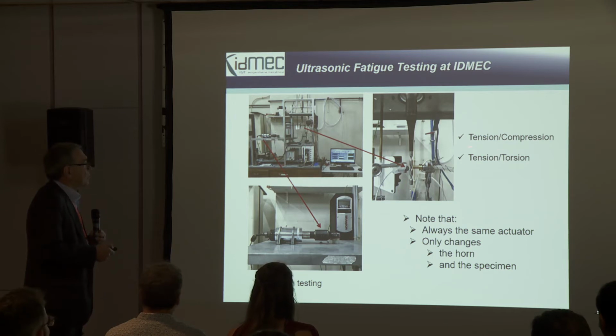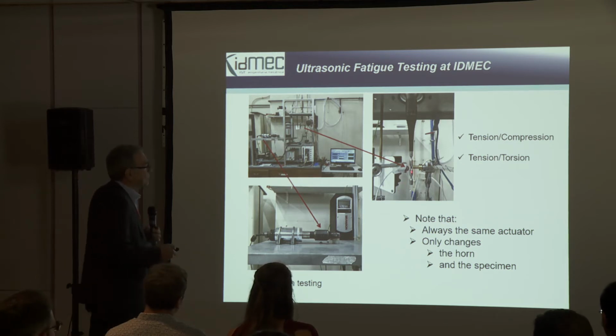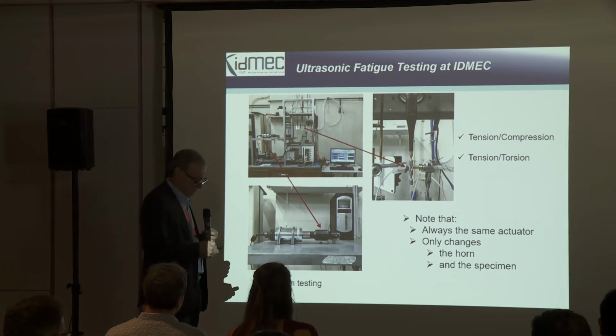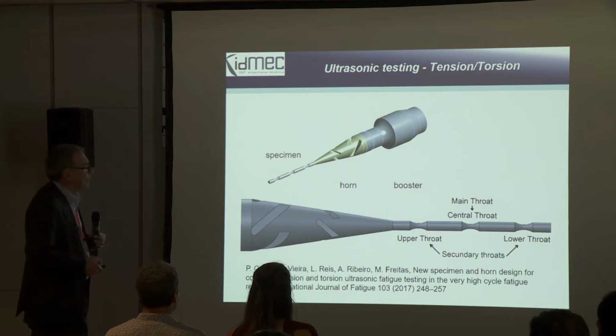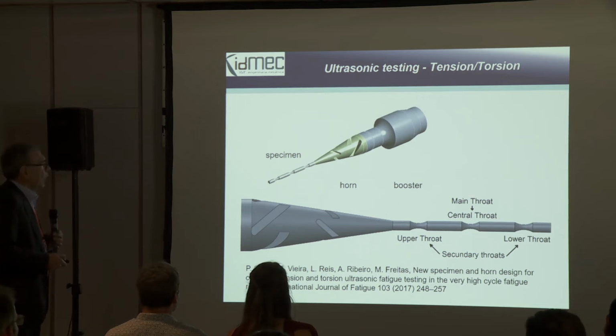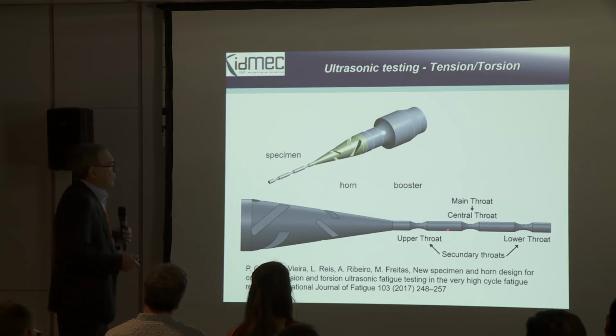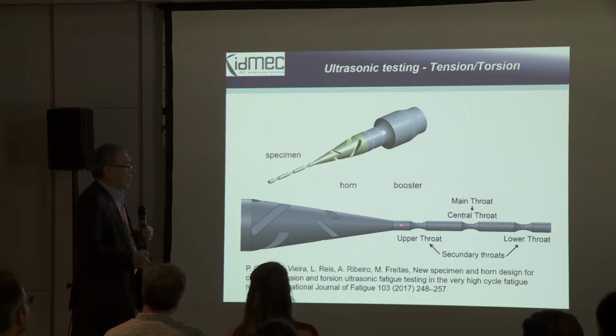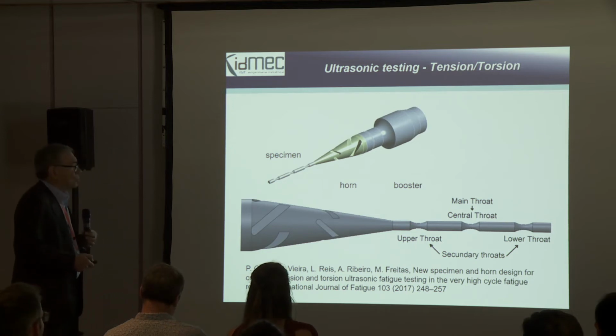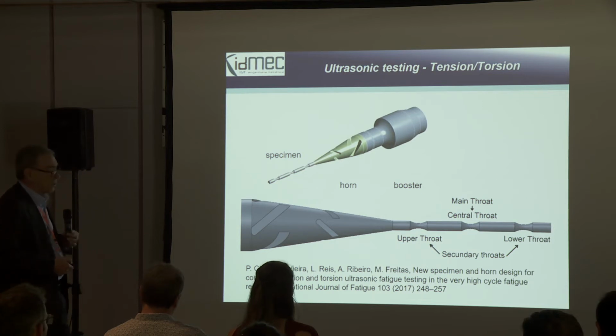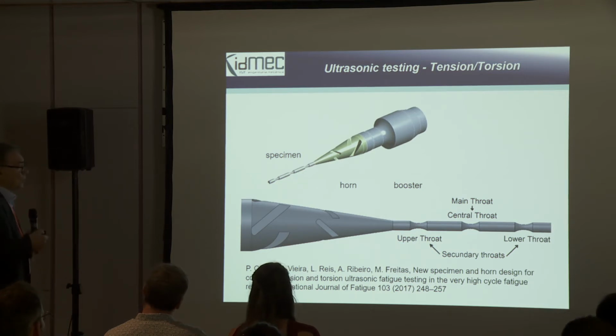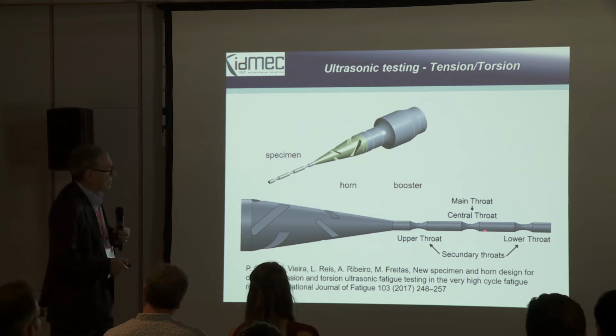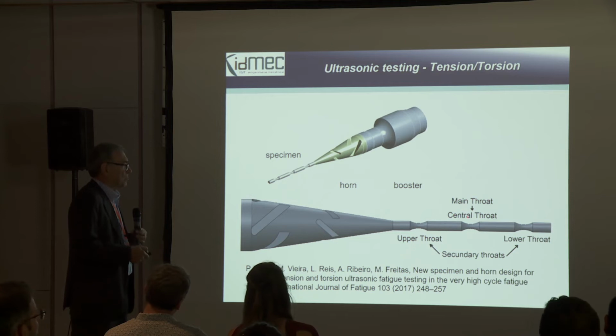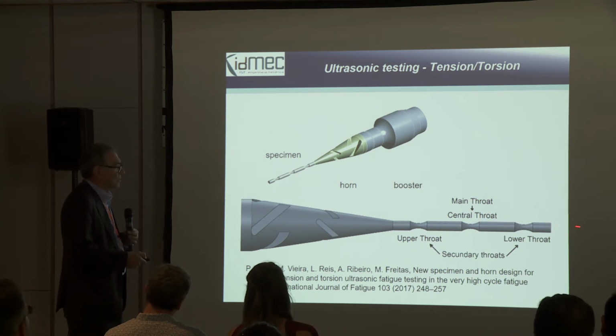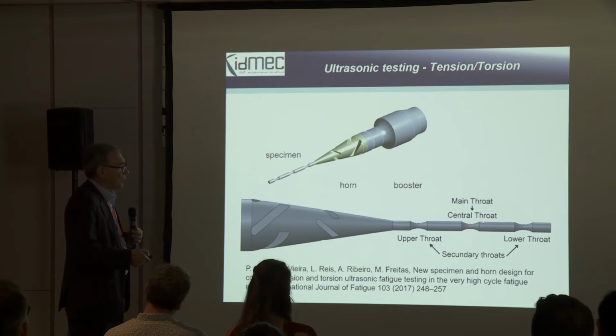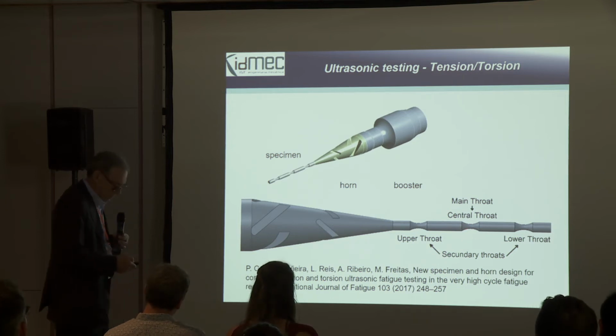And we can see, I'm not going to speak about the tension-torsion. You can see our tension-torsion specimen. We have 3 throats, 1, 2, 3. So this is the solution that we have for tension-torsion. Why do we have 3 throats? Because, see, of course, everything is in resonance, either axial or torsion. And as we know, the shear modulus in torsion is about 1/3 of the Young's modulus. So we must look for the eigenfrequency in torsion that relates to that. So we have maximum torsion here, maximum torsion there, and maximum torsion there. But axial, the maximum is over there. So what is interesting for us is only this zone.